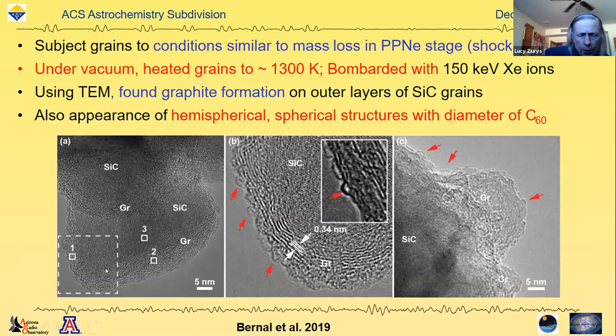The one box here is blown up. In the middle picture, you can actually see silicon carbide and then a striated structure on the edges. That's the formation of the graphite layers. It has a 0.34 nanometer separation. That's characteristic of graphite. And then you see on the edges little bubbles forming, little spheres and hemispheres. We believe those are C60.